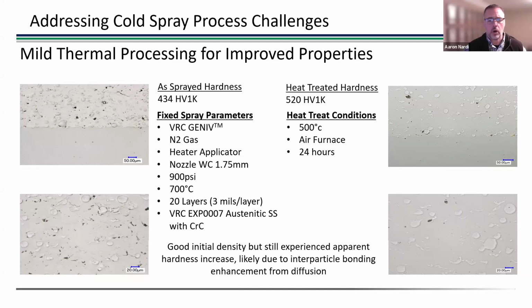So this is what you might expect if you actually put this material into service at these types of temperatures as well. And you actually see a hardening response. You see it go from 430 Vickers up to 520. That's a little bit of diffusion going on between that secondary hard phase, which is strengthening the deposit a little bit in that final condition.